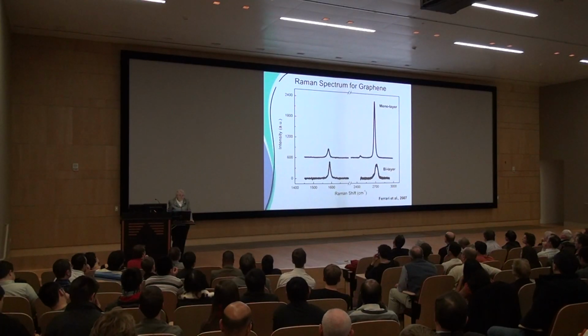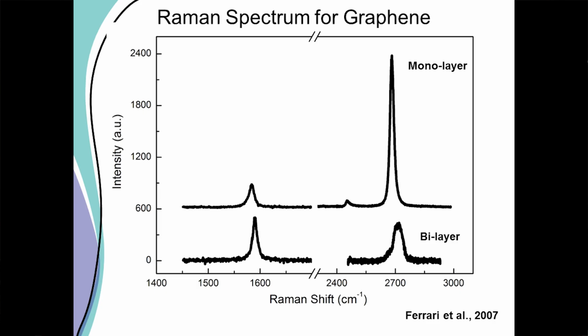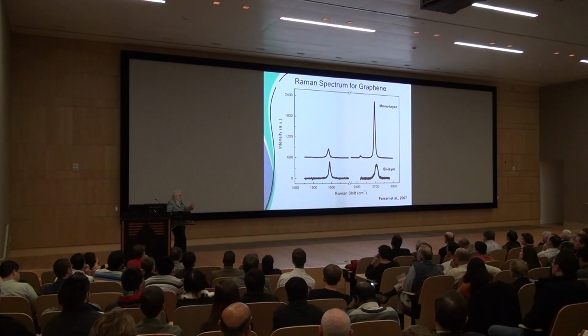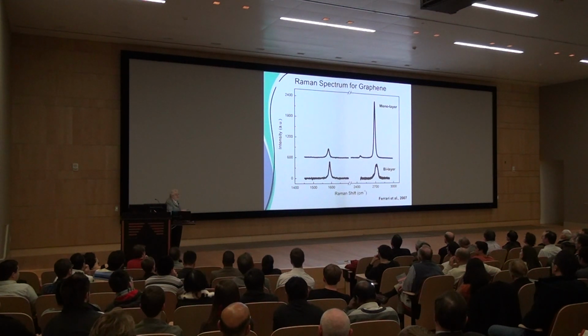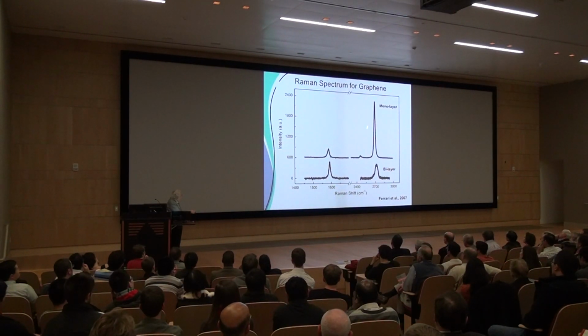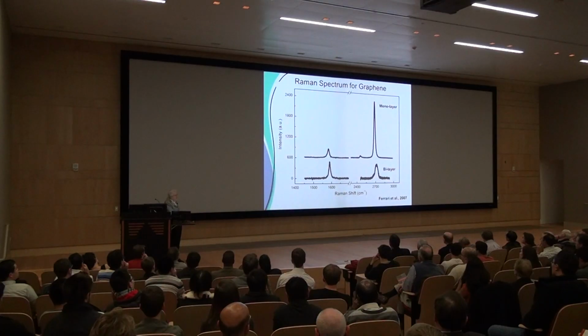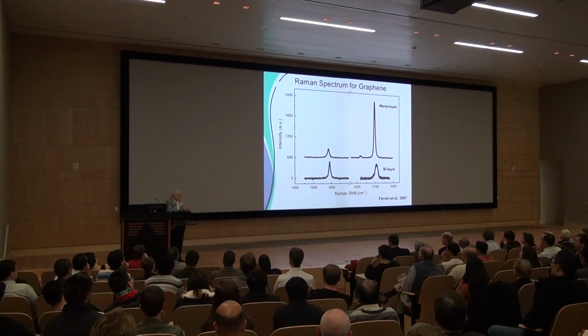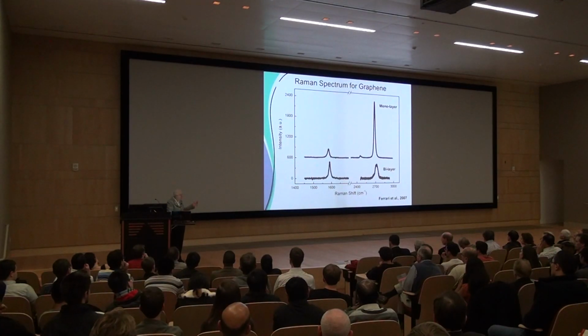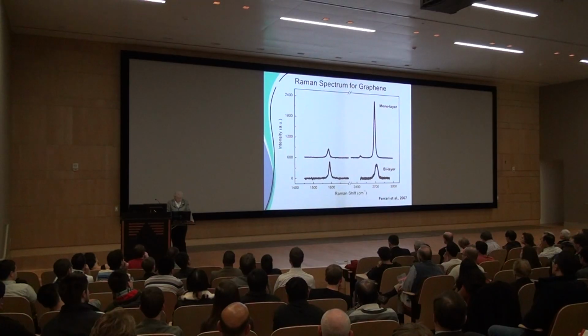Spectroscopically, graphene is very, very unusual. Normally, first order spectra are strong, second order spectra are weaker, third order spectra are very, very weak. However, here, because of the linear E versus K, amazing things happen. The first order spectrum, which is shown here, is this monolayer graphene. It's of certain size, and the second order effect is done in perturbation theory, so it should be small, right? But it isn't small. And it isn't small because you have resonance states in every single component of the second order process. So when you have all these three resonances, the combined effect is huge. So that's why this is such an unusual and interesting material.